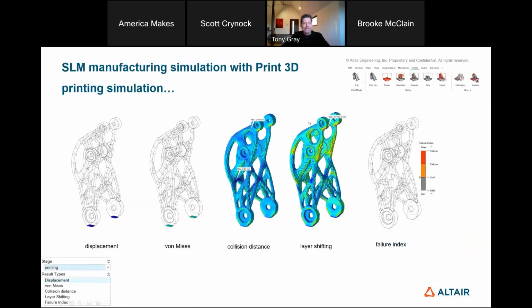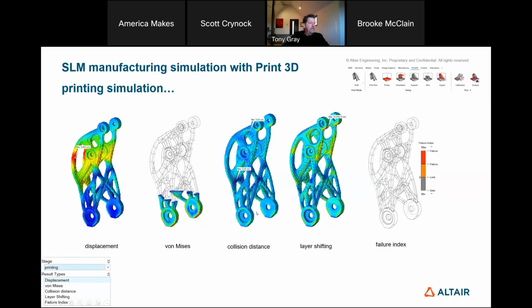So a bit fast there, but you can see that as the print runs, you can see the displacement of your part, get the von Mises stress. This is during the print process. An important result is this collision distance. You have a recoater height, so you want to avoid recoater strikes. So this is a very important metric as well.